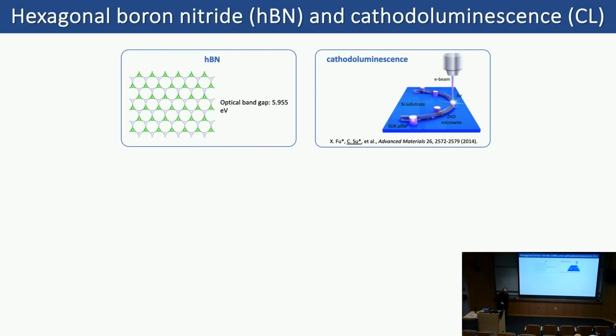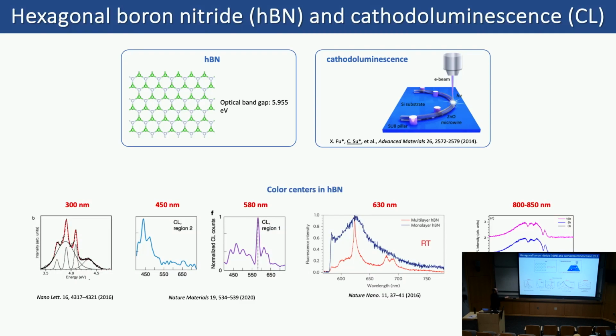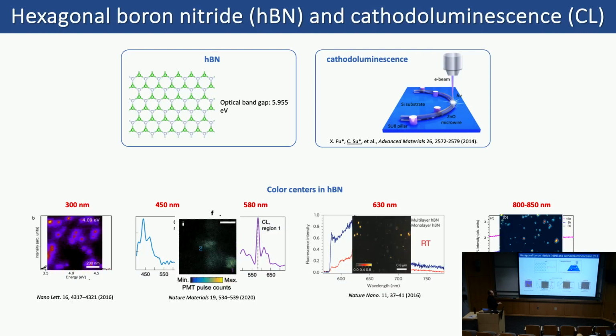The material I'm using is called hBN. So it's hexagonal boron nitride with a hexagonal lattice and an optical band gap of almost 6 eV. And we use cathodoluminescence to probe the emission spectroscopy. It's an equivalent technique of photoluminescence, but instead of using a laser as the excitation source, we use an electron beam. So that's the cathodoluminescence. In hBN, people have discovered a wide range of color centers, from UV all the way to the IR. But they all look like that.